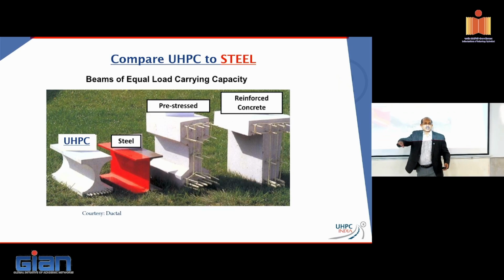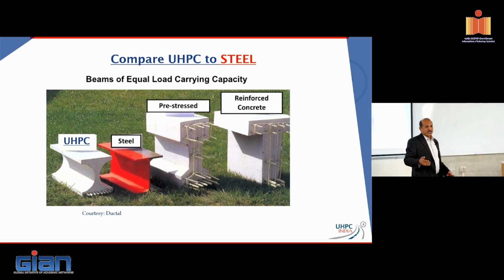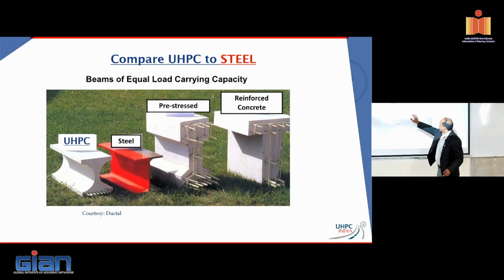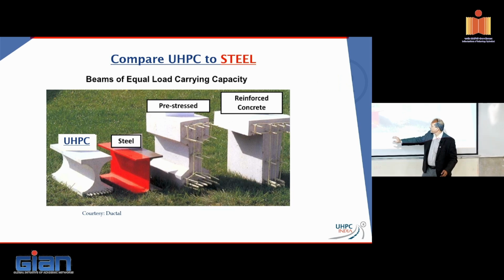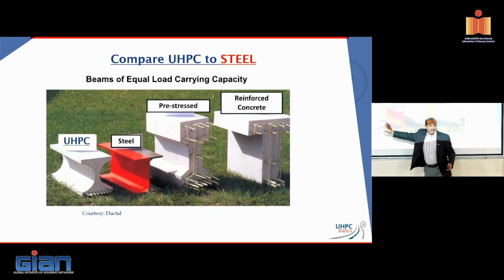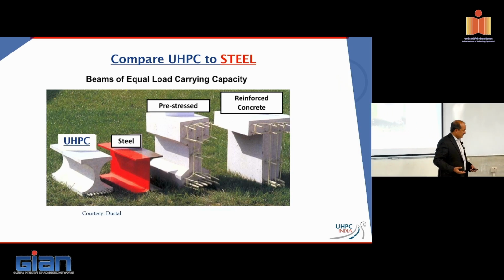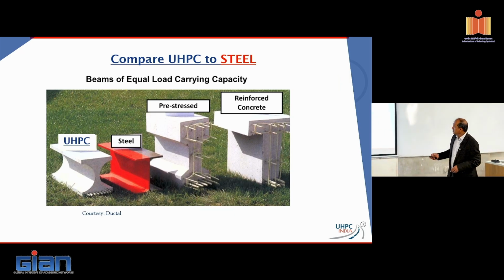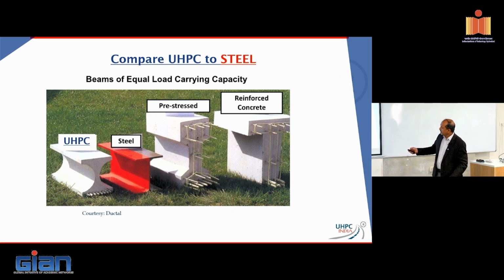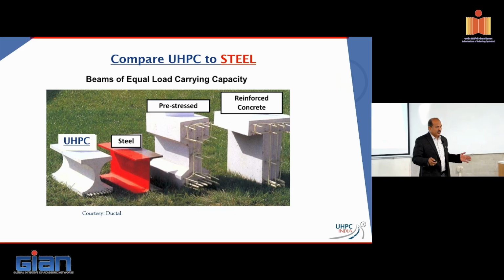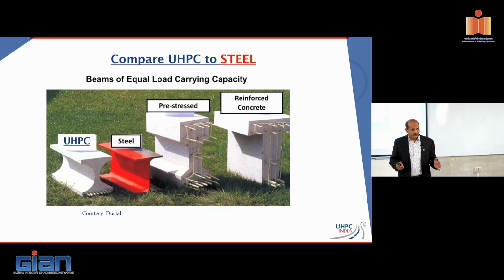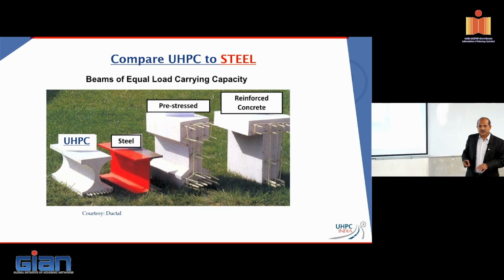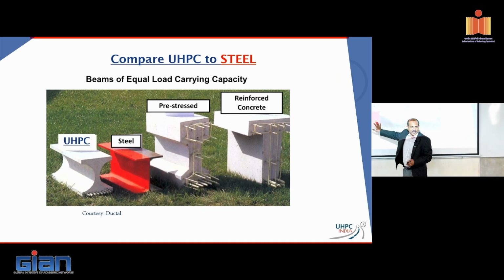Now, this particular slide is very commonly available over the internet, but it is a very impressive slide. It shows you where you stand with concrete and pre-stressed concrete, and where you stand between steel and UHPC. That's the beauty that UHPC brings about. It is also impressive that you can carve out these areas out of UHPC. That's what makes UHPC lighter. A typical pre-tension UHPC beam would be about 60% lighter than your pre-stressed concrete beam. And that is because of the properties of UHPC. So we'll talk a little bit about it so that we understand why we can come close to this.